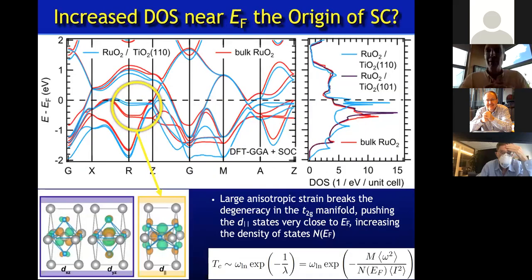Now, coming back to the properties, I just thought I'd tie this to what our collaborators have calculated from first principles calculations. This is using DFT GGA with spin orbit coupling in it, and they can change the value of U and so on. Okay, but the important thing to say is that what's robust about the calculation is that the density of states near the Fermi level increases for this strain state of putting 5% compression along the C-axis.